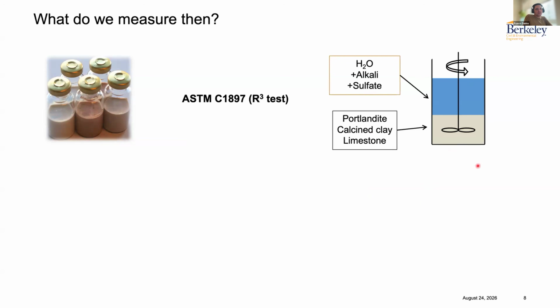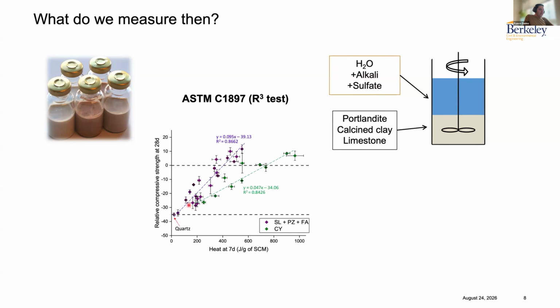So essentially what we do is that we make the SCM react in an ideal or an idealized pozzolanic environment, in excess of portlandite and alkalis and sulfate in the pore solution, and we then obtain a certain value of heat evolved in the case of the calorimetry test, and we can compare that with compressive strength.